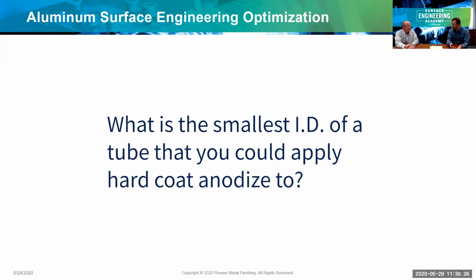Right. So there's a ratio typically that we would look at, Steve. What do we typically target there with getting hard coat down into the ID of the tube and the ratio? I don't remember the exact number, but it is documented. That's a good question, but yeah, anytime we see the need to drive coating down into the ID of the tube on the anodized side, we look at whether it's ID cathodes or means to get that electrical current down into the tube or into the ID and really build the coating. But there definitely is a concern and a limitation that we need to be considering up front at design.